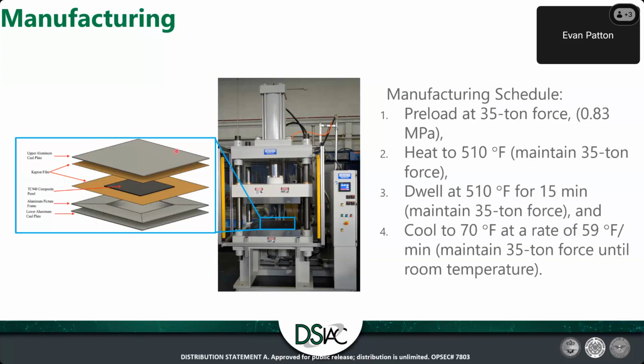And what we see on the left-hand side is the manufacturing stack up, or sandwich as we called it. That's essentially an upper and a lower aluminum caul plate. These basically just acted as sacrificial platens just in case something happened to the mold. And those are then bounded by an aluminum picture frame, which helped confine the composite, here in black, into its final shape. And these layers of Kapton film were just implemented for release from the mold.